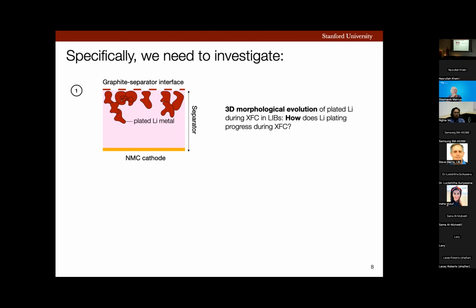What is the mechanism of battery failure? For example, do they form these sharp tip-like features that poke holes through the separator, causing battery short circuit? Or are they these flat, root-growing, mossy structures that cover the entire circumference of the graphite electrode, blocking lithium intercalation?